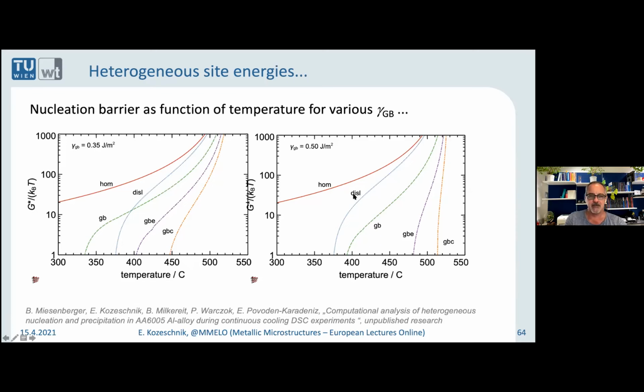It's dramatic. So if we have high grain boundary energy values, the nucleation barrier will disappear at grain boundary corners already at 512. If we have smaller values for the grain boundary energy, the nucleation can be suppressed even down to 460, 470. Yeah, but basically it solved the problem. It's now clear for us why the Mg2Si phase can nucleate. Also, with classical nucleation theory, one could never observe any of this precipitation below 400 degrees.